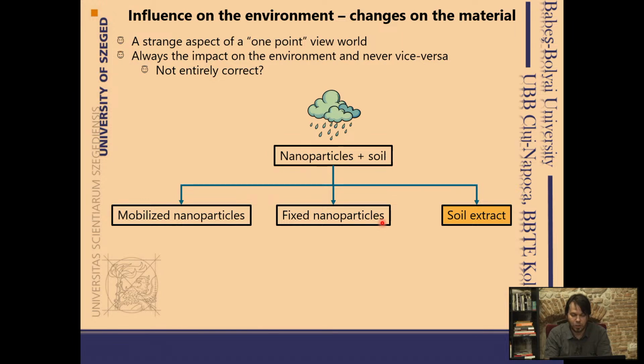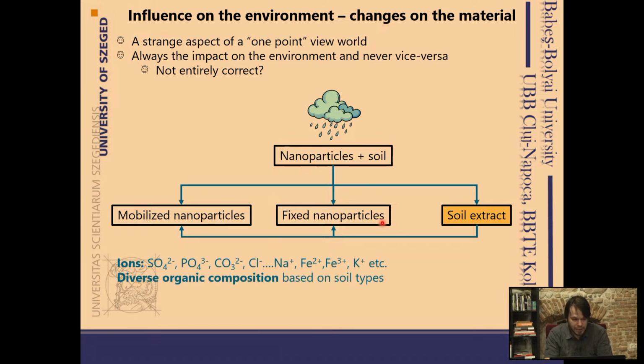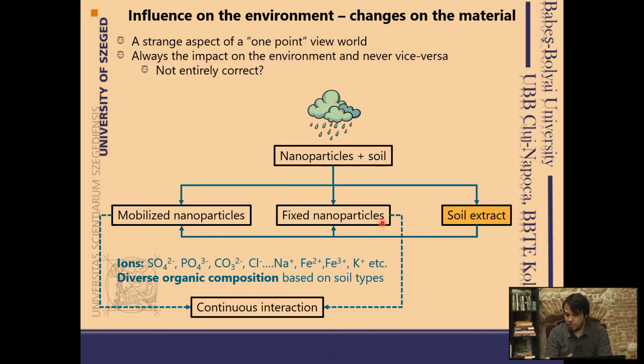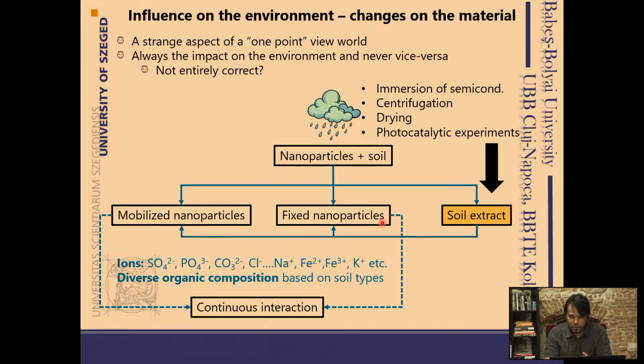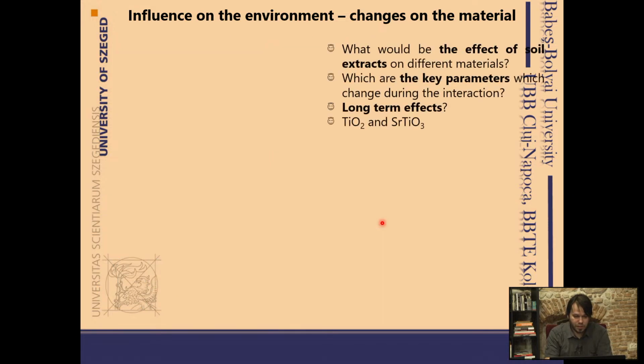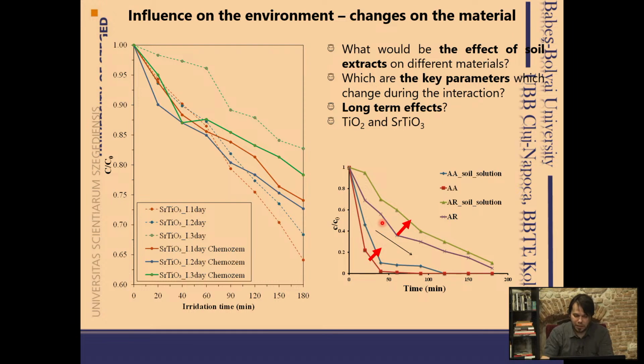As we have said, we have a quite complex mechanism in case of soil: mobilized nanoparticles, fixed nanoparticles, and of course, as I said to you, rain interaction with soils results in a soil extract. And of course, there are other ionic species which interact with these nanoparticles. And now, continuous interaction is of course nature's main issue. So we did a very similar experiment as we did with the Lemna minor, but this time we did a very simple approach, like putting these materials in soil extracts and tested their photocatalytic performance, which is in fact a way of testing their semiconductor properties. Everybody says that if nanoparticles are inert, they are inactivated in nature, but this was not the case.